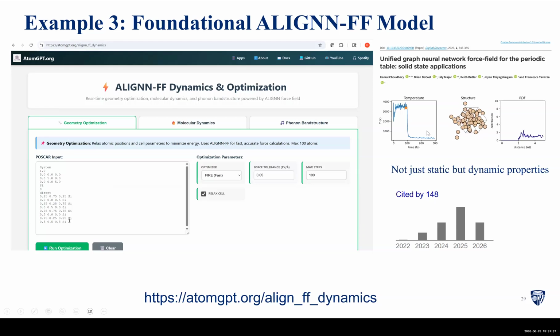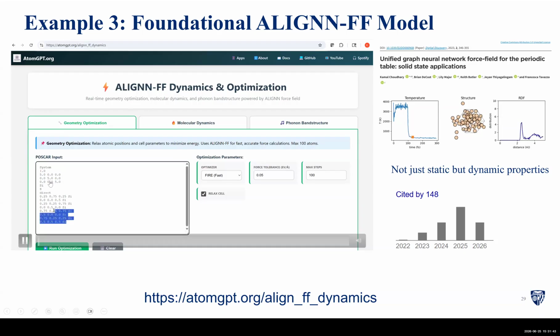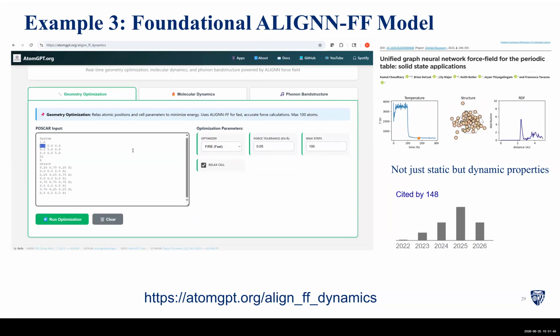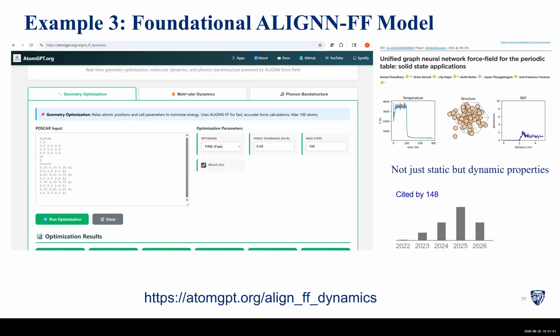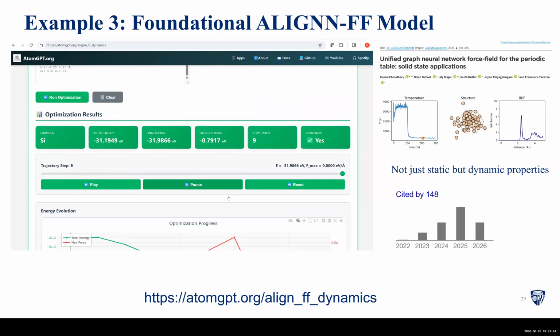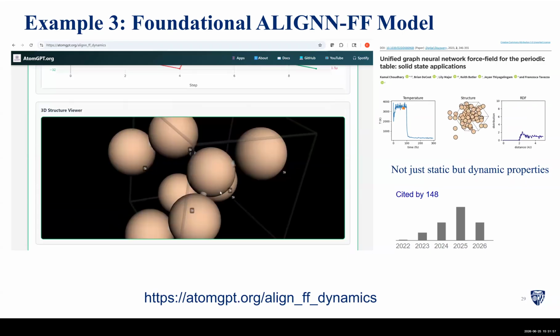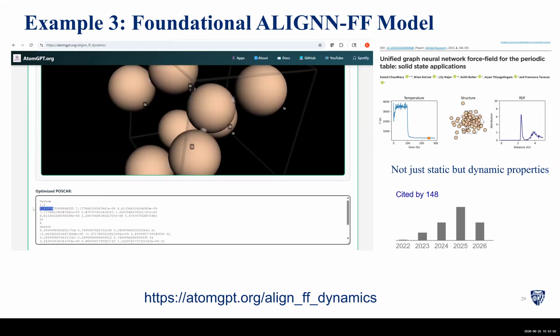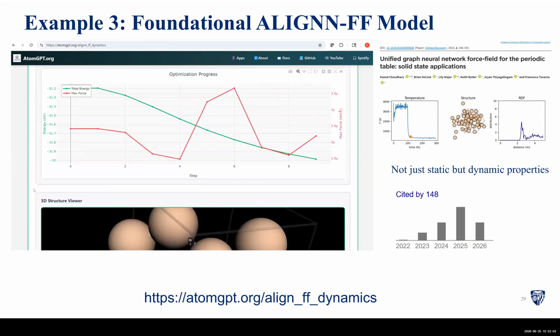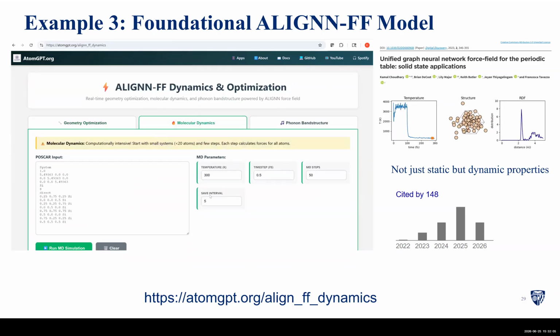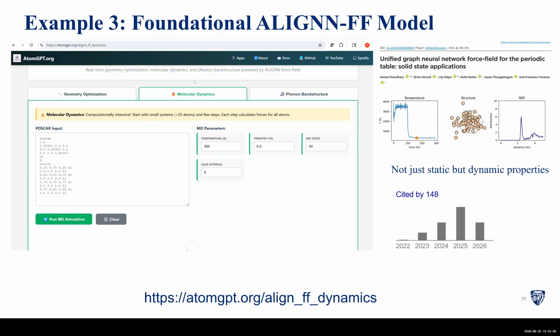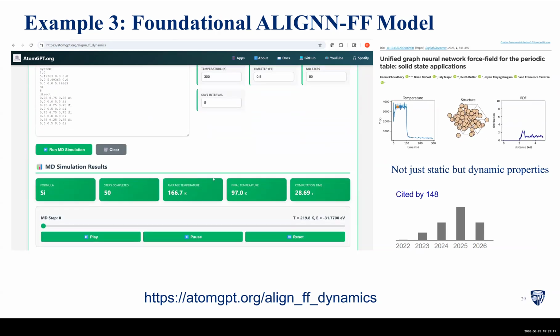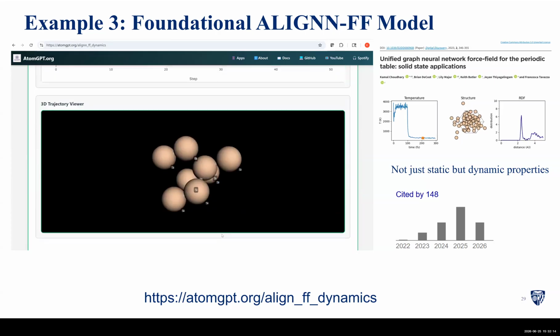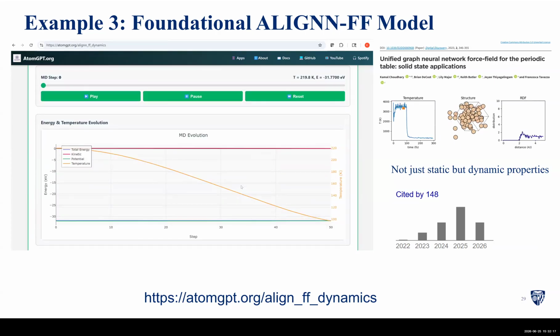Now we can also run molecular dynamics with it. So not just static properties, but also molecular dynamics. If you have an atomic structure for which we don't know the lattice parameter, we just give a random value of 5, for silicon, and then you can run optimization with this, and it will give you the optimum lattice parameter such as 5.43 or 5.47. Yeah, 5.46 or 47. Not just that, you can run molecular dynamics for an atomic structure. Like if you have a system and you want to predict what will happen after a certain number of time steps, you can make some cool movies with this and see the mechanism of certain phenomena.